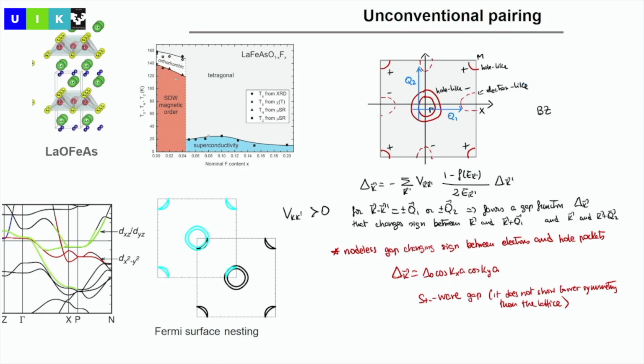Now, the difference between the Cooper pairs here is that you are dealing with different types of pockets, so with electron, with hole pockets. And therefore, you can still keep your S wave. You don't have to go through a node to have this change of sign between positive and negative. And this is what we call the S plus minus wave gap, that it shows, in fact, full spherical symmetry, the gap function, but it doesn't have nodes.